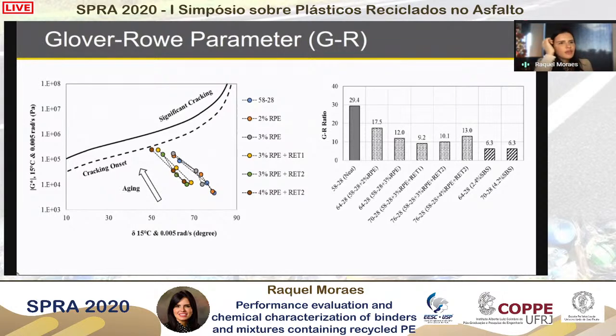And on the right side, we have an aging index calculated considering the Glover-Rowe parameter, considering the short-term aging binders and long-term aging binders. And we can see that both the recycled plastic binders, and the recycled plastic binders containing the terpolymer, had very low aging index in terms of the Glover-Rowe parameter in comparison to the neat binder, which can indicate a reduction in the aging susceptibility of these materials. However, in comparison with the SBS binders, the SBS binders outperform the plastic modified binders in terms of the aging susceptibility.